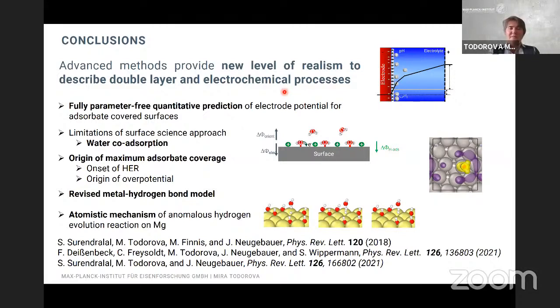In particular, I looked at the platinum water interface and the co-adsorption of hydrogen, and discussed the limitations which we have in the surface science approach due to the neglect of water. I was hopefully able to convince you that we have an idea of the origin of this maximum adsorbate coverage that can be reached for the hydrogen, which is connected to the onset of the hydrogen evolution reaction and the origin of the overpotential. And we propose a revised picture for the metal hydrogen bond within this system.